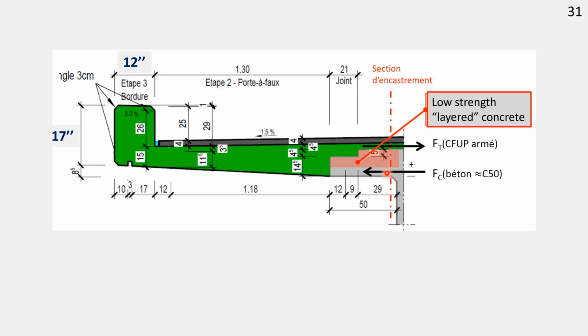Fortunately, the bottom part of the slab was, however, in excellent condition and had a very high strength. So I needed to look at the design in order to verify whether it's possible to neglect the middle part of the concrete as a contribution to the shear resistance and, of course, also bending resistance. And then I could confirm that actually this is possible to leave it as it is, as a low strength concrete, and to rely on, of course, the UHPFRC here as a tension cord, and then the reaction force in compression can be taken by a sufficient amount of healthy concrete.